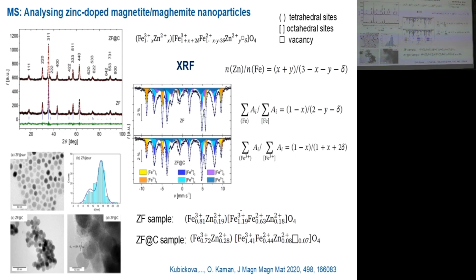But it is even more powerful. Like in this case, we prepared some zinc-doped iron oxide nanoparticles by thermal decomposition. Actually, there were two samples. And in literature, it is often assumed that the samples from the thermal decomposition are based on magnetite, that it is really stoichiometric magnetite. But usually researchers do not prove it.